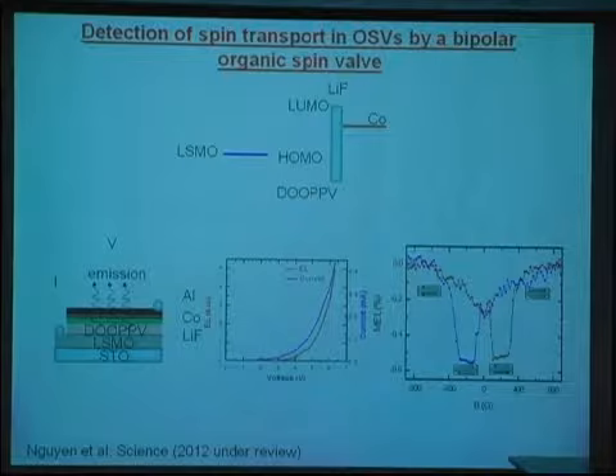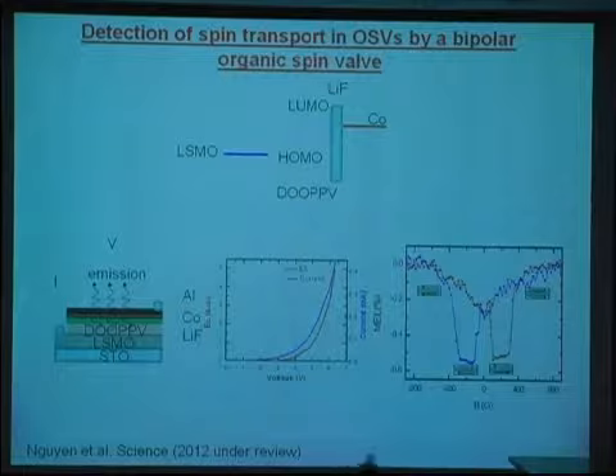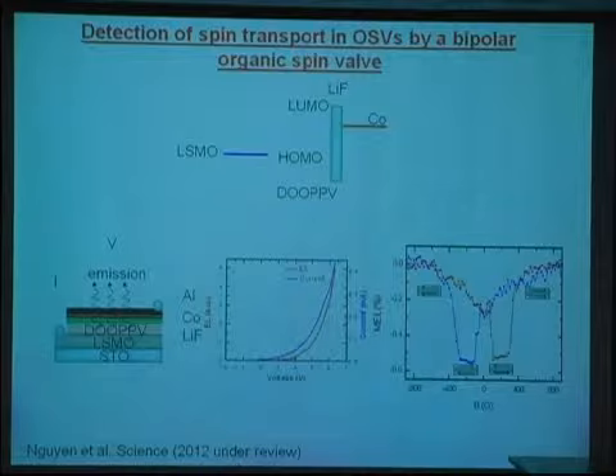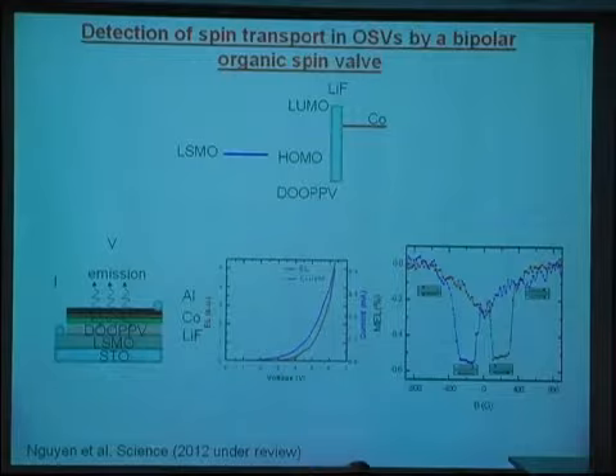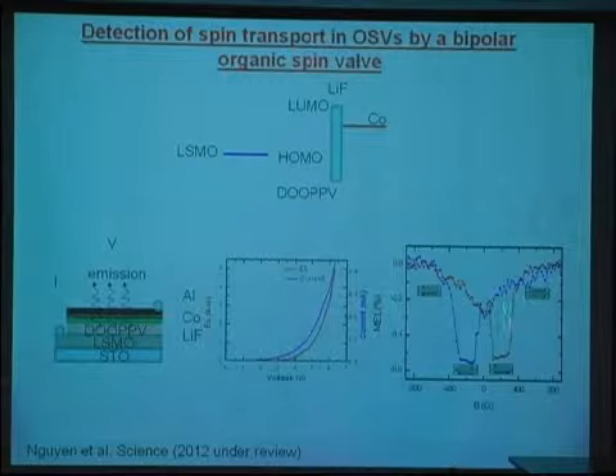the materials. Yes. Okay, so I understand your argument that you're making there, because you say you inject from both sides, they do recombine, otherwise you wouldn't get light out. Yes, yes. And if this recombination now depends on your spin polarization, you see the hysteresis like this. Then your argument is that the spin state has to be conserved until they meet. Yeah. And that would be a proof of transfer.